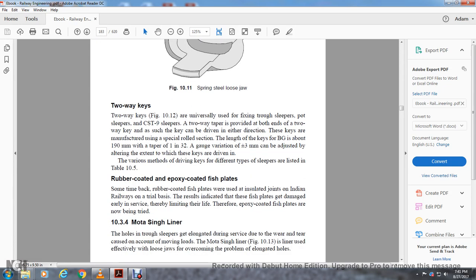Rubber coated epoxy coated fish plates. Sometimes rubber coated fish plates have been used with the insulated joints of the Indian Railways on a trial basis. Results indicate that the fish plates could get damaged early in service, thereby limiting their life. Therefore, epoxy coated fish plates are now being tried.